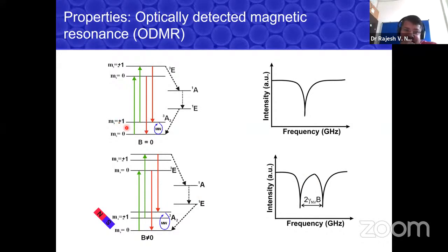Okay, so the other application of NV center, as I said, is magnetometry. If you have these NV centers with a ground state triplet and excited triplet, you excite it, you have a transition from up to the down level, then you have a slightly delayed transition. You start with an equal population in this level. At one optical cycle, you reach a level where ms equal to 0 has more population, and this is called optically induced transition in the system. And if you apply microwave, because this frequency is around 2.87 gigahertz, you can manipulate NVs between these two levels. And if they go from ms equal to 0 to ms equal to plus or minus 1, you can read that out optically as a decrease in fluorescence intensity. And this is the way you can manipulate the spin state of the system optically and read out optically.